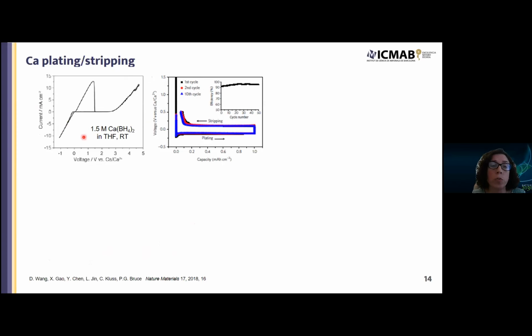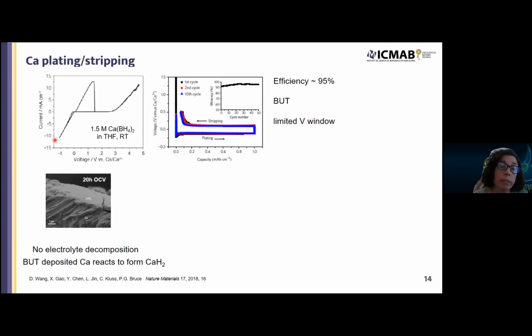Later, other studies were done with other alternative electrolyte formulations. So the group of Peter Bruce reported this formulation with much higher efficiency despite lower stability upon oxidation. And in this case, there is also formation of a sort of native SEI between the deposited calcium and the electrolyte, and it consists of calcium hydride.